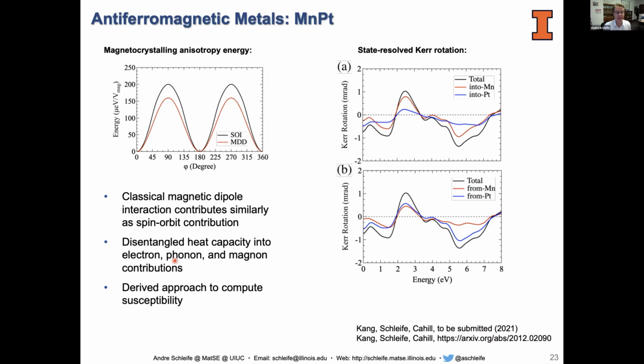We also can use these techniques to study electron dispersion, phonon dispersion, and magnon dispersion, and by doing so, we can disentangle those individual contributions to the heat capacity of electrons, phonons, and magnons. And so in this case, for instance, we found that in this material, simply because of how these dispersions work out, the phonon contribution is the dominant term at low temperature. Magnons don't actually dominate there. And we also derived an approach to calculate the susceptibility of the material.